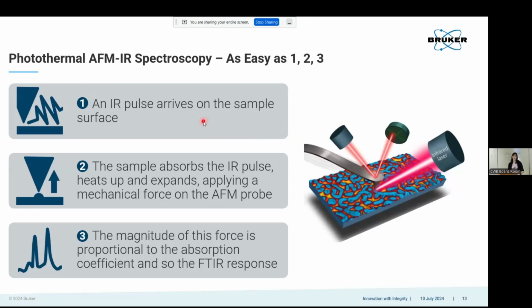So obviously we're not going to go way into the weeds of how this works, but a simple mechanism is up here. What we do is we shine a laser onto the tip sample area, so that atomically sharp point for the AFM where it's scanning over the surface. And we use an infrared laser and we're illuminating the surface with that. And so if the sample absorbs that wavelength of infrared light that you're shining on the surface, so let's say we're using that 2926 infrared light again, you're going to take in that energy in the molecules and they're going to heat up because they've taken in energy. And that heat up is going to cause them to expand and move outward.